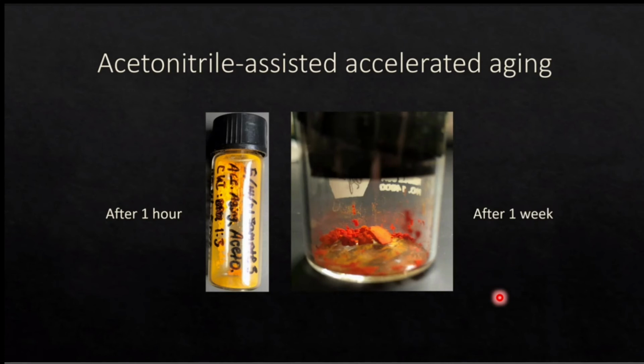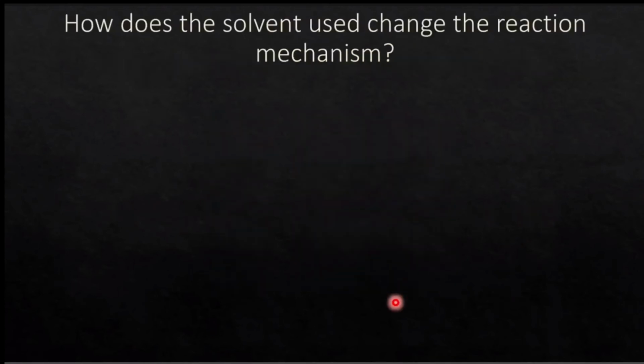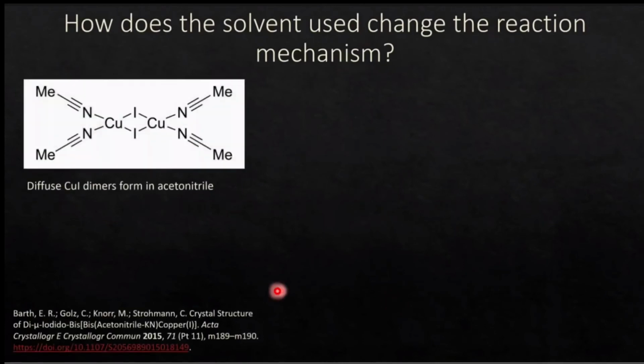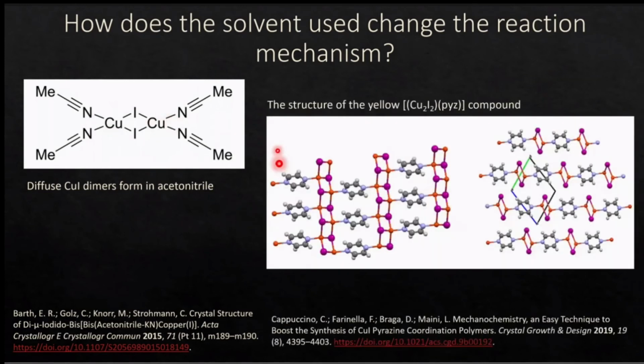And we wanted to understand how the solvent can change the reaction mechanism so much. And so that was our big question. How does this happen? And so we found a study by Barth et al. that actually looked directly at how copper iodide solvates in acetonitrile. And we found that copper iodide forms these dimer structures that are surrounded by 4 acetonitrile molecules that are coordinately bonded to the copper.